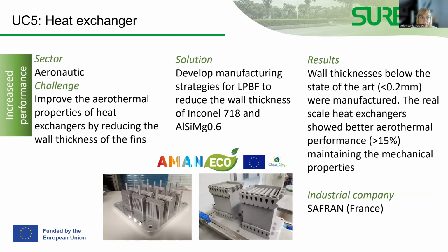The next use case is a heat exchanger for aeronautics. Here, the aim is to increase the performance. Safran was the company behind this, and they wanted to improve the aerothermal properties of the heat exchangers. And for that, they wanted to reduce the wall thickness of the fins. So they had some specific designs of the heat exchangers to be manufactured by additive manufacturing, but they wanted to reduce the fins because this would bring a major improvement in terms of aerothermal performance. So we developed different manufacturing strategies for laser powder bed fusion in order to reduce this wall thickness in two materials, Inconel 718 and an aluminum alloy.